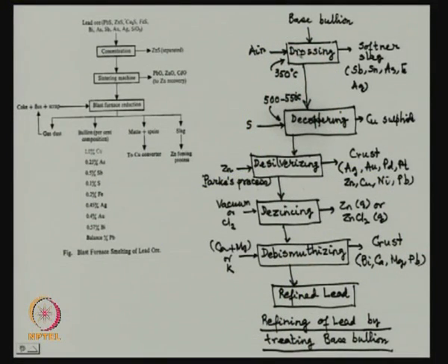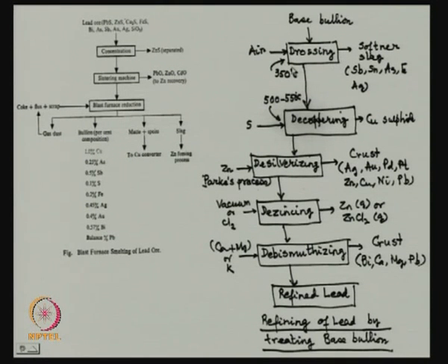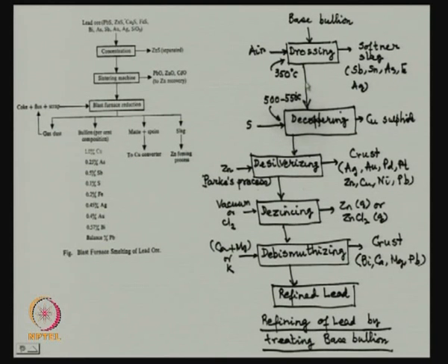These processes have been used for centuries and evolved out of trial and error. First of all, there is the step of drossing. The melting point of lead is very low — 327°C. The base bullion is kept just above the melting point in a suitable furnace. Air is allowed to blow mildly and continuously; if it is stirred, many impurities will form oxides, float up, and are skimmed off. After that, it goes to a slightly higher temperature, 500 to 550°C, when sulphur is added and copper is taken out as copper sulphide.